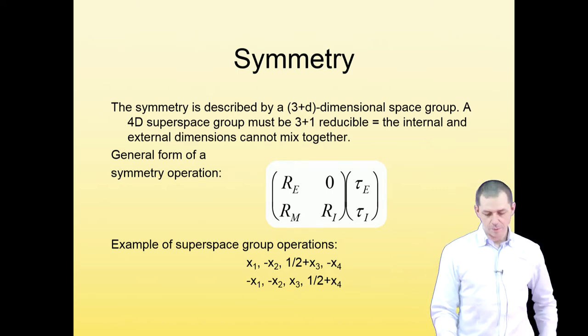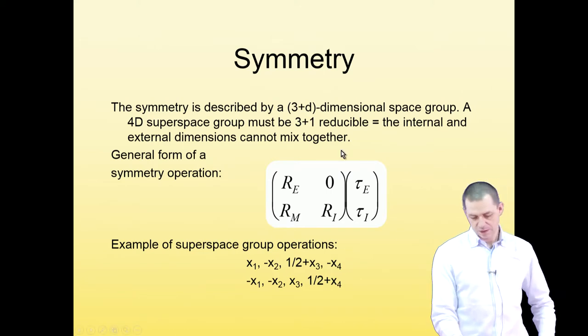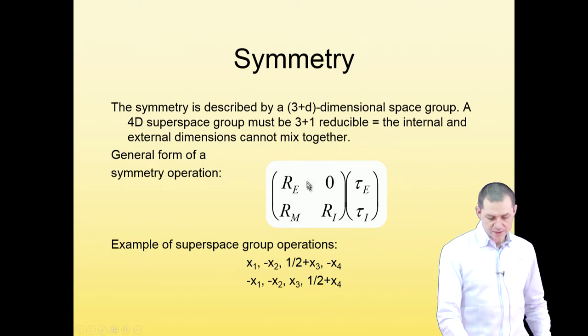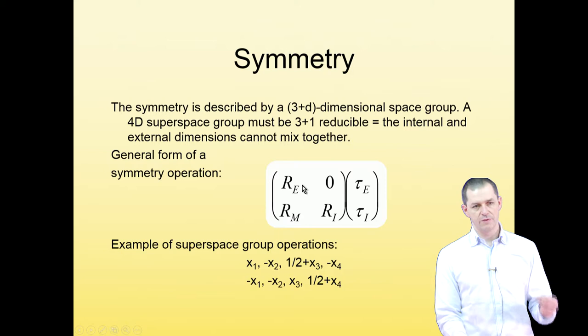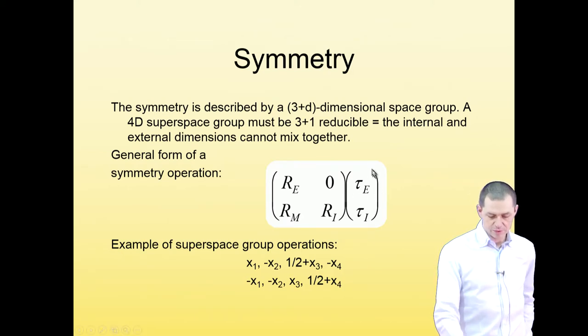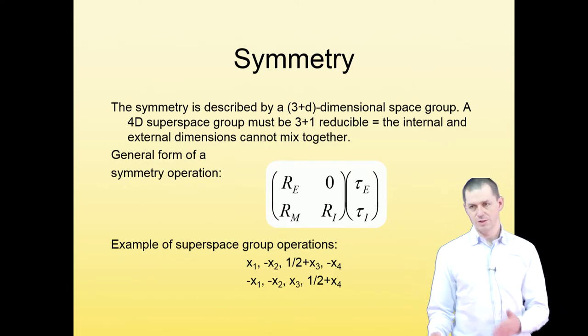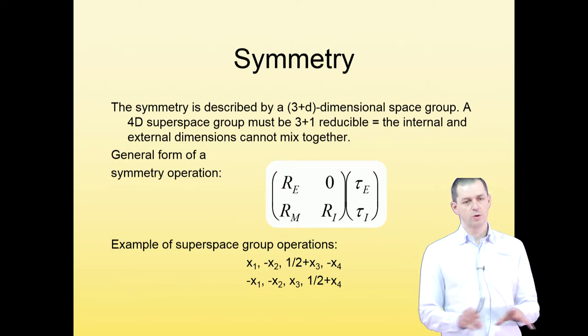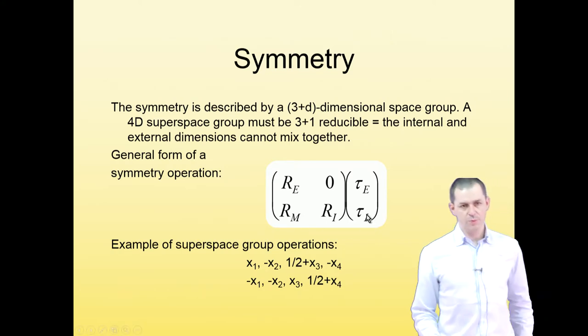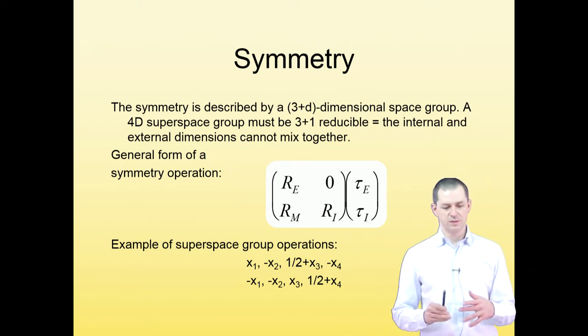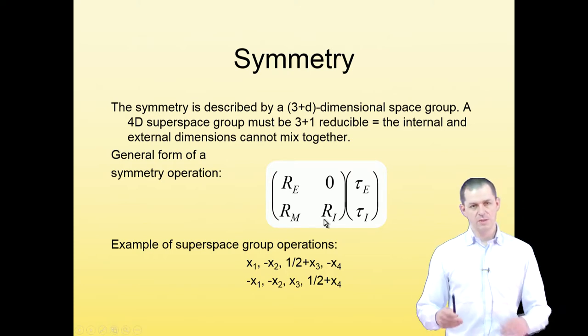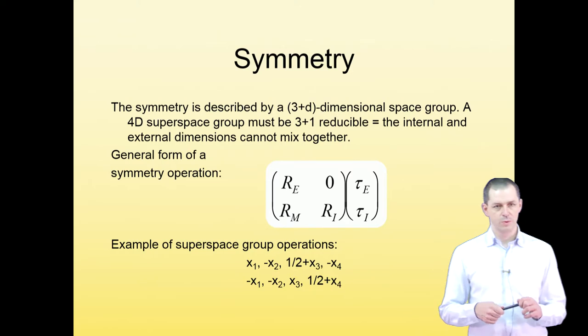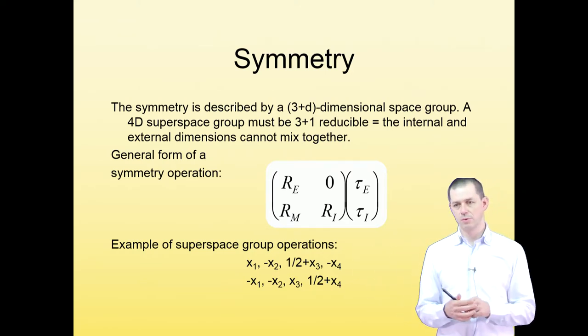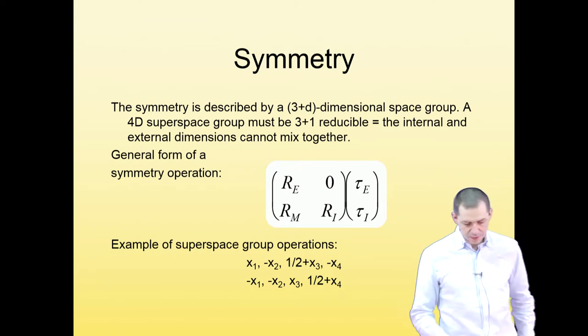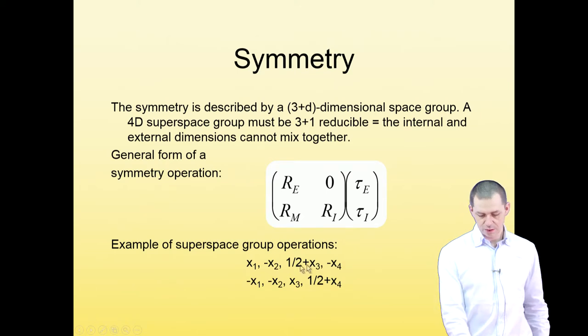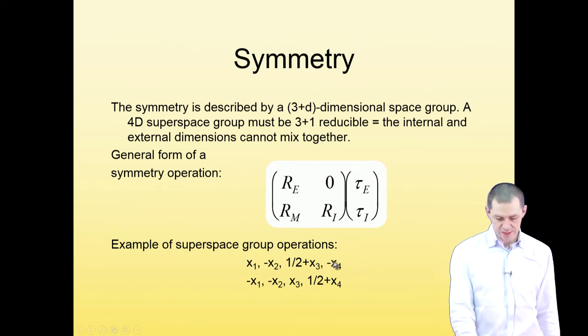And the general form of a symmetry operator looks like this. The key part, without going into details, is that it has a three-dimensional part which corresponds to the symmetry of the average structure. And it has a three-dimensional translation part, which again corresponds to the translational part of the symmetry operator of the average structure, so if you ignore modulation. And then you have parts that correspond to the changes in the modulation phase. So that part here describes the symmetry in the additional dimensions, and it actually corresponds to the shifts and inversions of the modulation functions in the structure. So this is an example of a superspace group operation. You see it looks like a normal space group operation. It just has one dimension more.